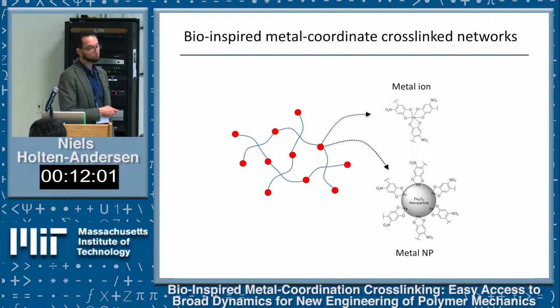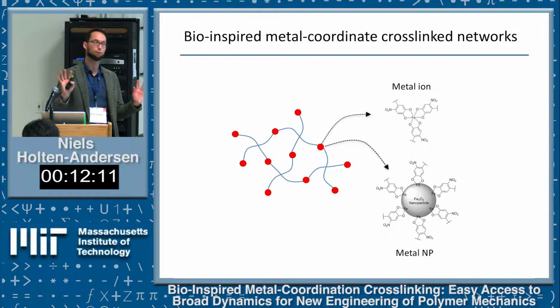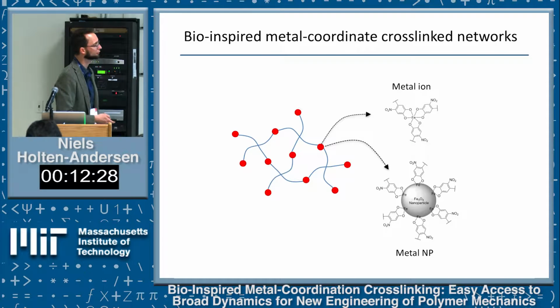Okay, so the two stories I'll tell you quickly are about how we've been using these insights to demonstrate various types of hydrogel networks. We're using this same 4-arm polyethylene glycol polymer throughout—we're not even switching the polymer for any of this. Basically we're now just playing with different types of metal ions, and we've also begun doing work where we add metal nanoparticles as the cross-linking structure. I'll show you we get dramatically different properties in the materials depending on whether we use a metal ion or a particle.